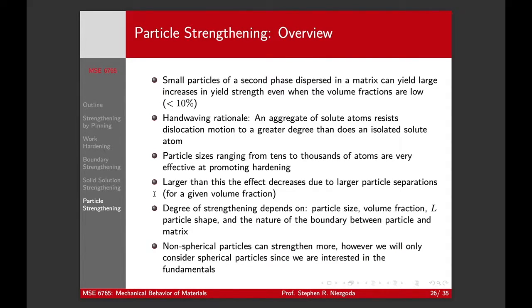If your particles get much larger than this, the effect decreases because the separation between the particles for a given volume fraction goes up. So remember, our degree of strengthening depends on that L prime in the denominator. So if our obstacles get very far apart, then this effect goes down.